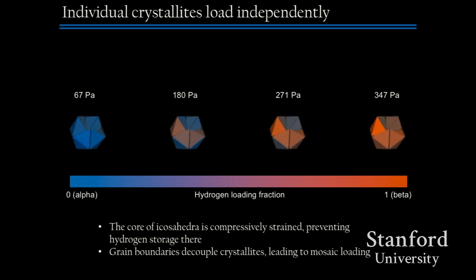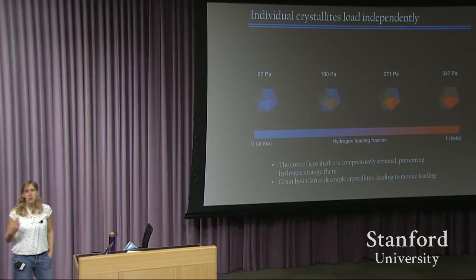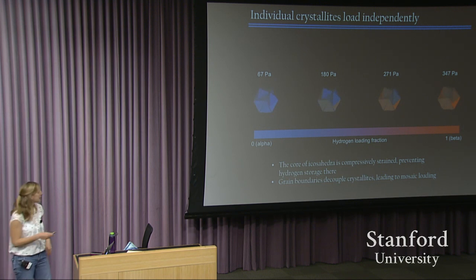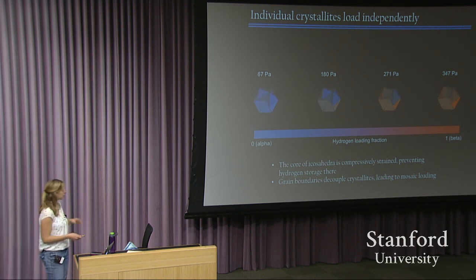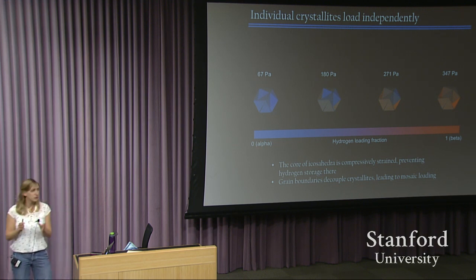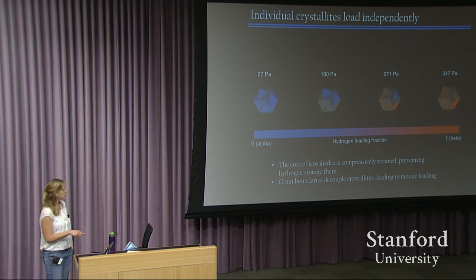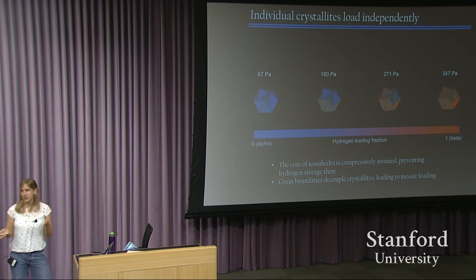So to sum up this part, the core of the icosahedra is compressively strained, preventing hydrogen storage there and basically reducing its energy storage capacity. And then grain boundaries are essentially decoupling all the crystallites within the nanoparticles, leading to mosaic loading, or a loading where different parts of the nanoparticle basically transform at different pressures.